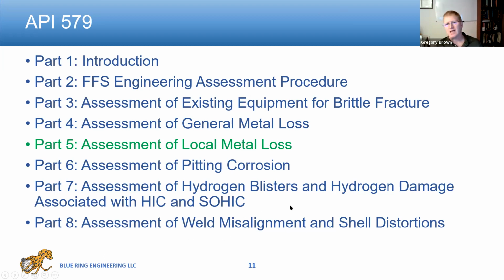Part 8 is about misalignments. A pressure vessel should be round, gives us a nice even hoop stress field. If it's not, we start getting higher stress, bending stress. This can actually lead to a failure, very often due to fatigue. The guidelines in Part 8 will tell you how to assess those types of out of roundness, weld peaking type situations.